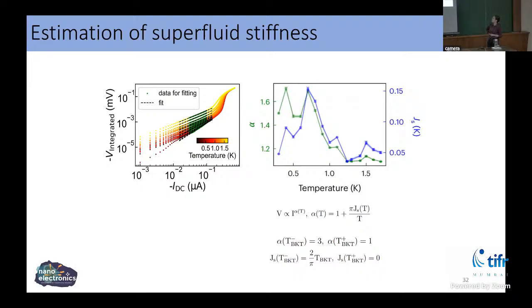And you can see that it never quite reaches 3. And there is no sharp jump. Now, how do we explain that? This happens because the system is inherently disordered. This sharp jump I can theoretically see only in the clean limit of the system. Now, we have talked about how there is lattice relaxation and different local twist angles in the system, and that inherently makes my system disordered. So it was foolish of me to even expect that I would see this sharp jump. So there is actually no clean BKT transition happening. Nonetheless, if I apply these equations, I can estimate the superfluid stiffness. And that's what we did.